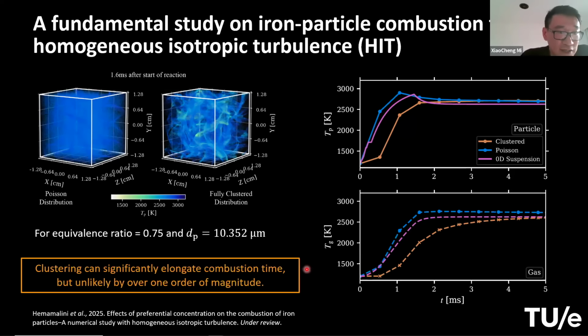Then we see this clustering can indeed significantly elongate combustion time, but this effect is not that significant, it does not increase the combustion time by more than 1 order of magnitude. It's just several times longer, right?